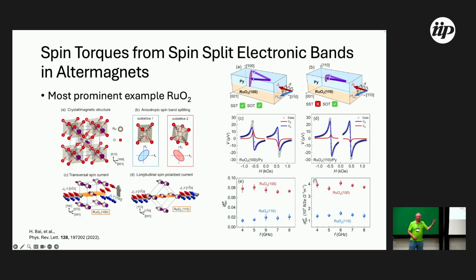Okay, so I thought I'd bring up just one example. This is where they do spin torque ferromagnetic resonance. So they pass a current through ruthenium oxide, which is like the bad boy of altermagnetism. Most papers are written on ruthenium oxide, but there is a big discussion on whether ruthenium oxide is even magnetically ordered. So take all the papers on ruthenium oxide with a grain of salt. It's possible that by using epitaxial strain, you turn it into an antiferromagnet, but the bulk material itself presumably is not magnetically ordered. So do you know the band structure of this material?